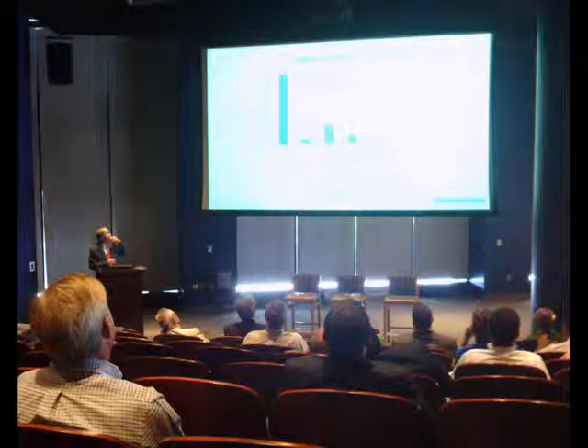I think I'll skip some of this stuff. The Penn State pump testing, different biodiesel blends, 0, 12, and 20%, 7 pumps at each fuel blend, both ultra-low sulfur and number 2 oil, 7,000 hours of operation. Again, this 5-minute on, 1-minute off. The metric here was seal leakage, and we worked with the pump manufacturer on a very precise measure of seal leakage rates and quality, and these are very low. These are how many drops do you get? So the bottom line is that the seals leaked less. Their seal rating was better at the higher biodiesel blend levels. So both with ultra-low sulfur and with number 2 oil, less seal leakage with the 20% blends than without the biodiesel in there. So our basic conclusion is we're not seeing adverse effects that would give us a technical blend wall for biodiesel.